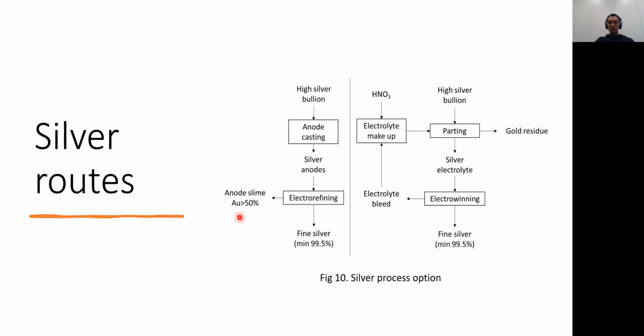I have two options here for silver routes. For high silver bullion, the first route is anode casting. This bullion will be casted into silver anodes, and these anodes will be processed through electrorefining. In this electrorefining, it will produce fine silver, minimum 99.5%, as I mentioned, regulated by LBMA, and also anode slimes. As we can see, it goes through one, two processes to produce gold. And usually this electrorefining process takes 3 to 5 days. So the gold will be close to the deadline for shipment to the gold mining company. So this is not preferable, but it is the most robust process.